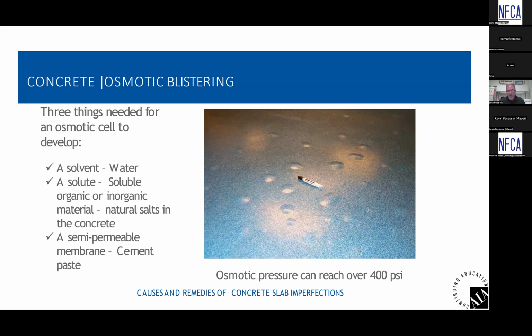And when you look at the tensile strength of concrete, it's typically 10% of the compressive. Concrete has a compressive strength commonly 3,000 to 4,000. So the tensile strength or integrity of the concrete is roughly 300 to 400 PSI. And these osmotic cells can create pressures that are over 400 PSI that can cause blisters at the surface of the concrete, fracture in the concrete. I've seen it where they